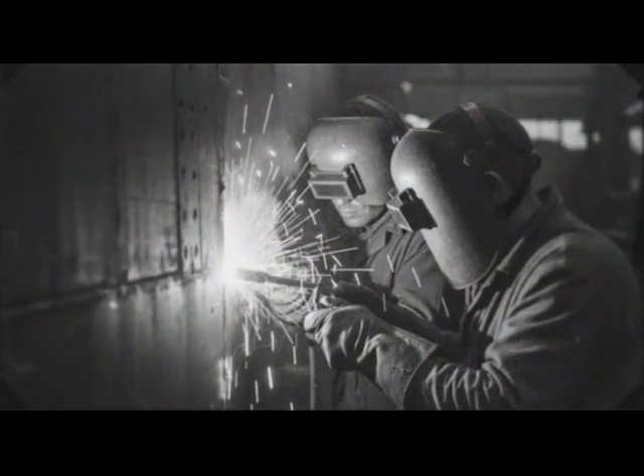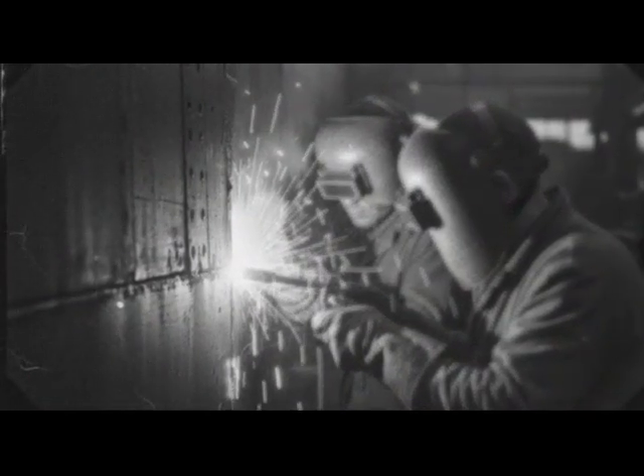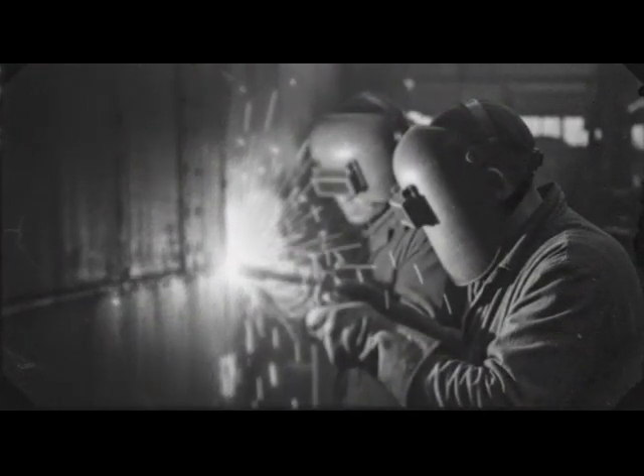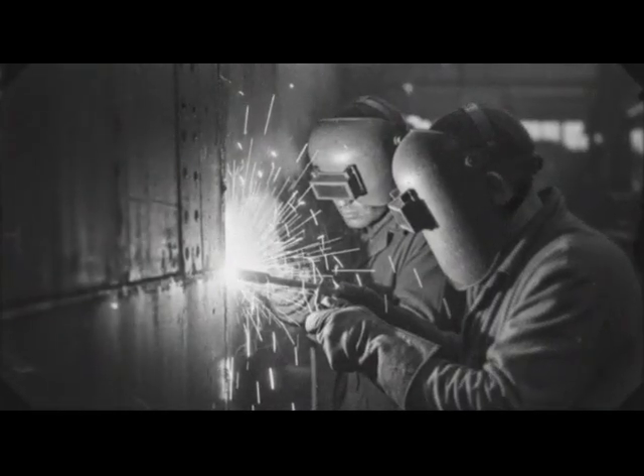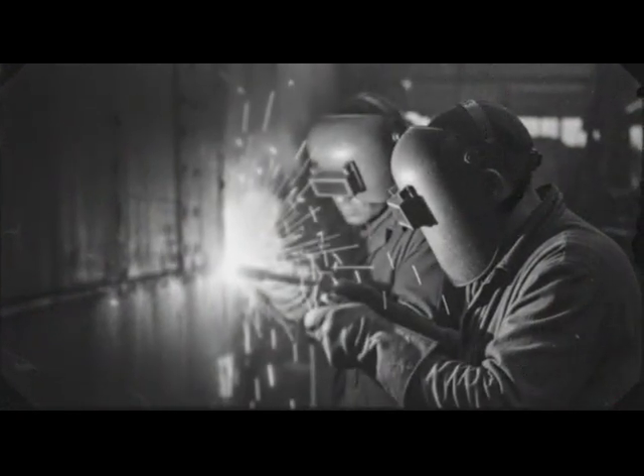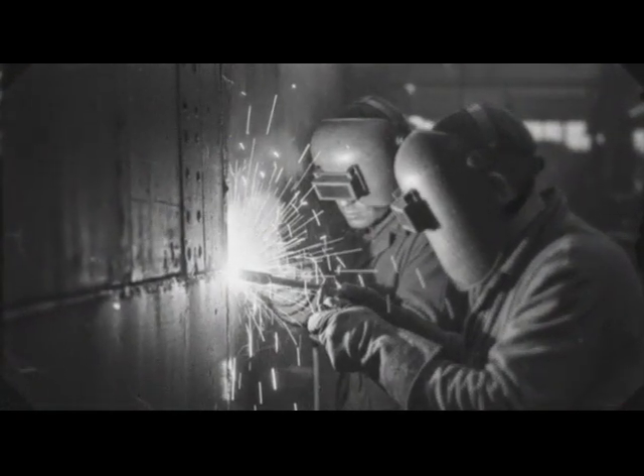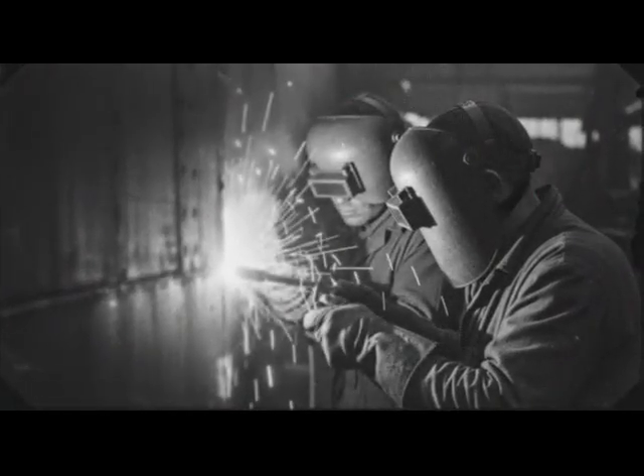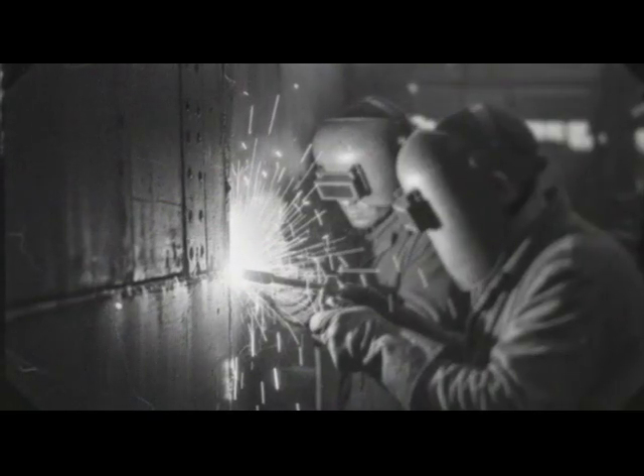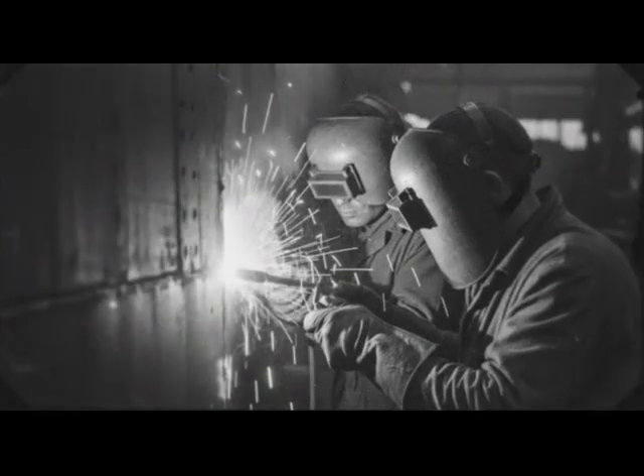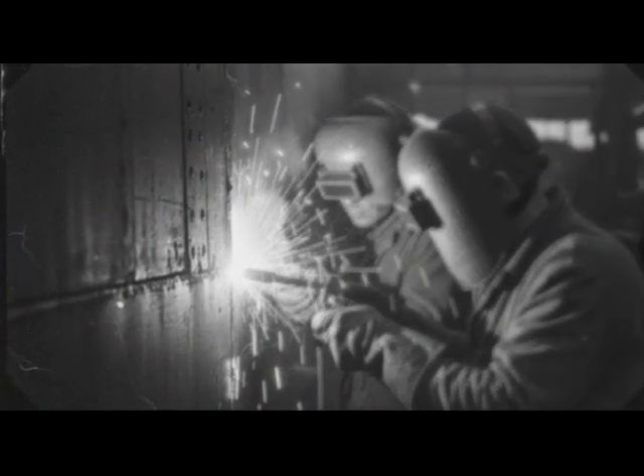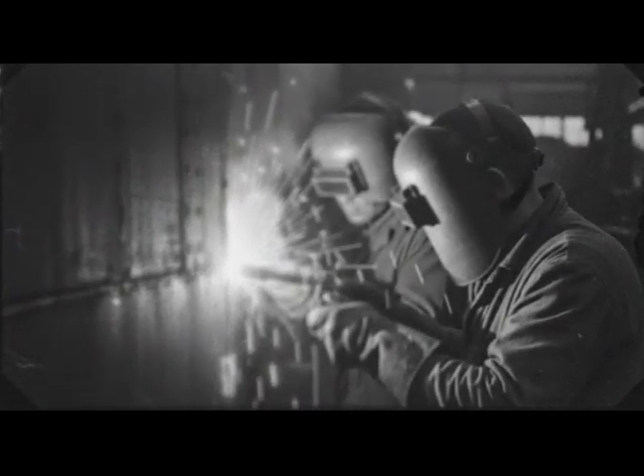Riveting, used in some hull sections, showed similar degradation in quality. Rivets were improperly set, not fully seated, or made from inferior materials. Each imperfect rivet was a potential failure point. Under extreme pressure, these weak spots could initiate catastrophic hull breaches. The submarine might survive 1 deep dive, 2, 10, but eventually the weakest point would give way. And once the hull was breached at depth, even by a small crack, the pressure differential would tear the submarine apart in seconds.